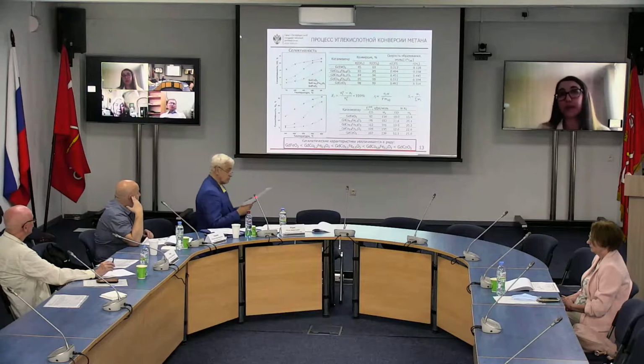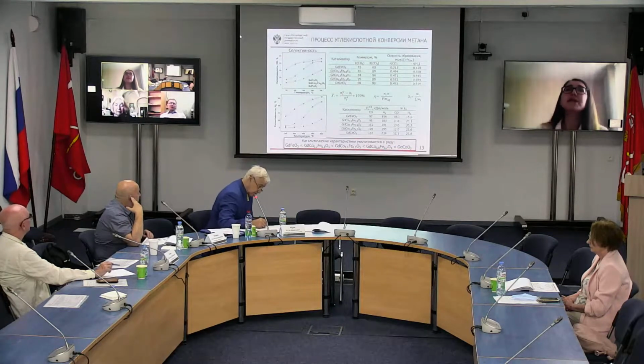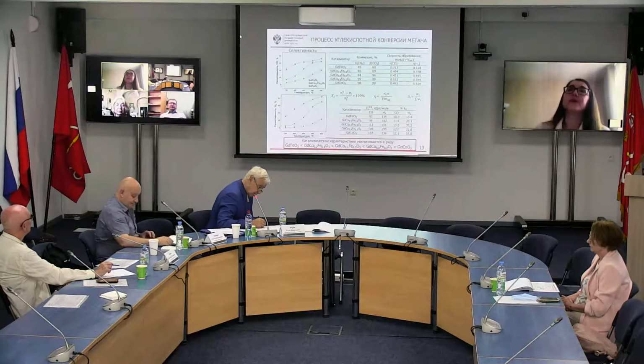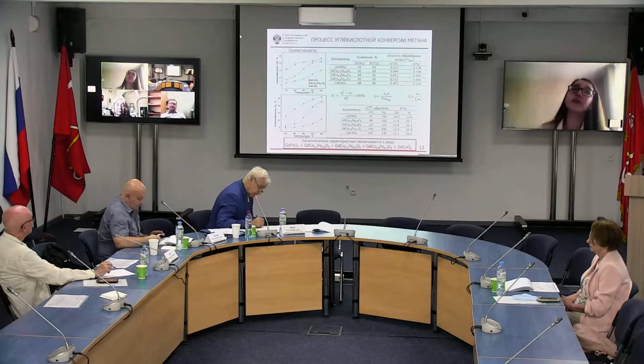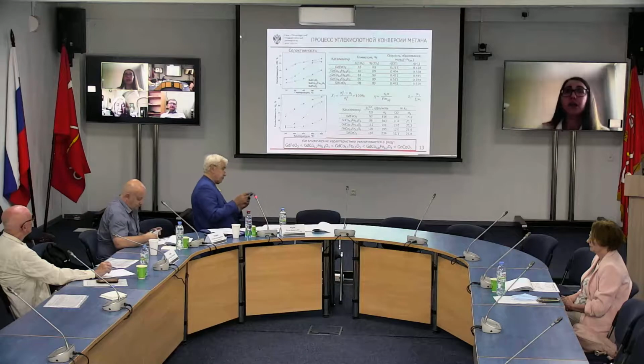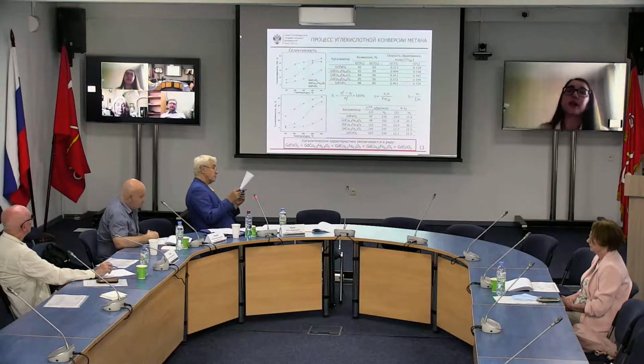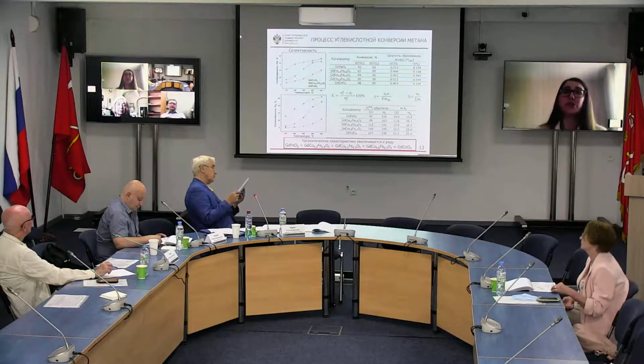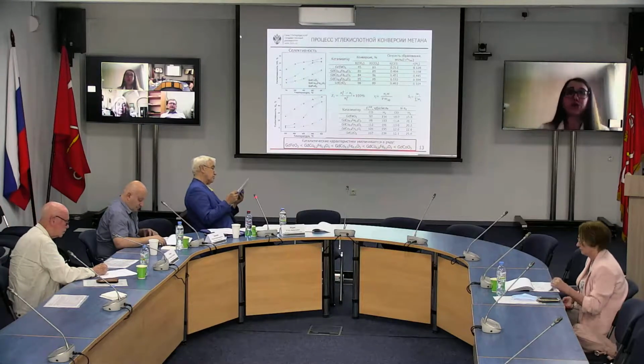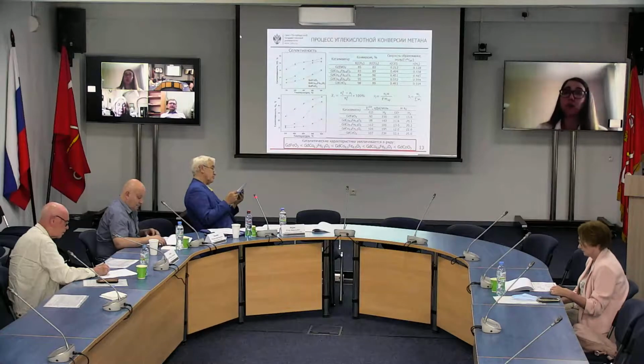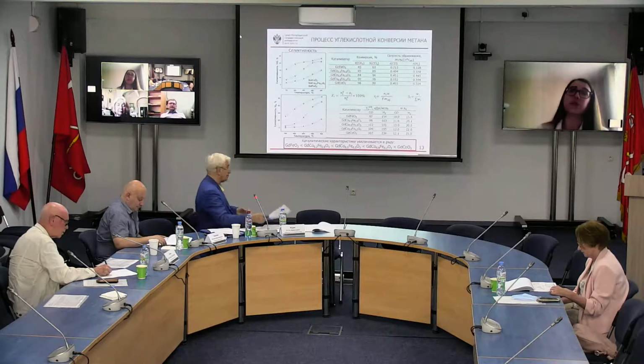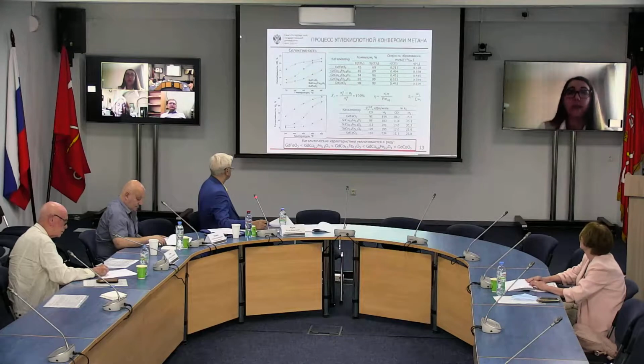And when we administer small amounts of cobalt, we see the formation of solid solutions. There is still activation of hydrogen, and the growth of the energy barrier is compensated by the pre-exponential factor value. And the growth of the logarithm that characterizes the number of active centers is associated with an increase of selectiveness in hydrogen. And for carbon monoxide, there's no similar correlation. And this confirms the fact that in the centers of these oxides, we have the adsorption of carbon oxide.